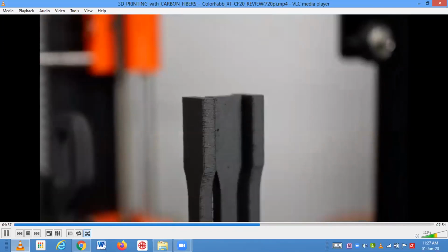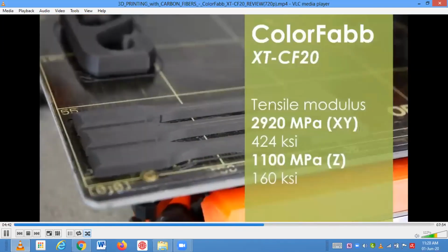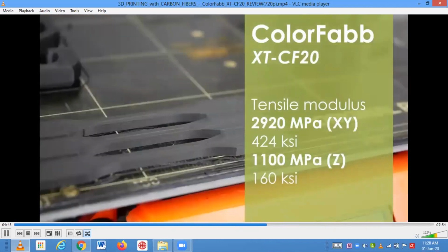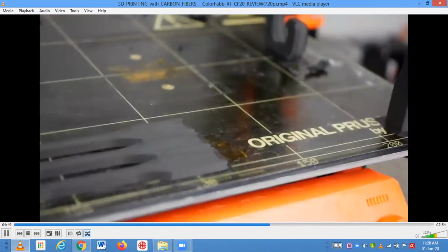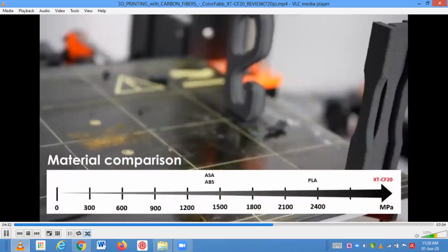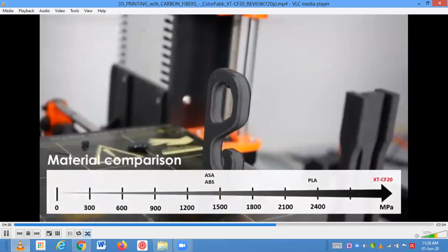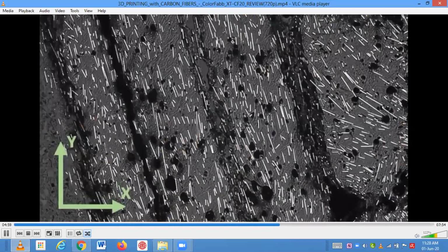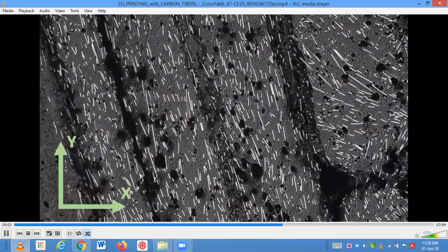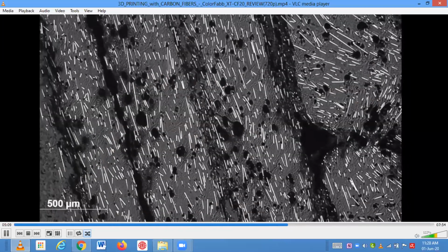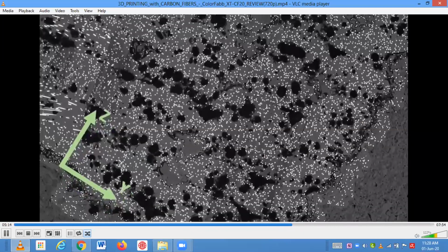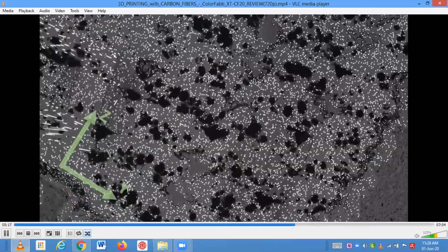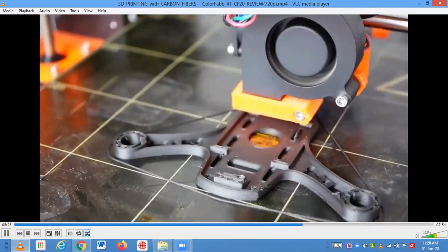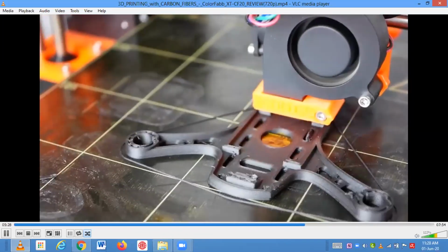The tensile modulus, so the stiffness of the material, is what really stands out, because with almost 3000 megapascals, it is the most rigid material I printed so far. This is the first time I also tested the stiffness perpendicular to the printing direction, so the upright specimens. If we take a look at a microscope shot of the material, we see that the carbon fibers orient themselves in the printing direction, and these fibers give the material its superb rigidity. Perpendicular to the printing direction, they are only barely adding strength and stiffness, which is verified by my second test that showed a tensile modulus of only 1100 megapascals in this direction. So keep this in mind with your designs. If you use fiber-reinforced materials, they have very different properties in and perpendicular to the printing direction.